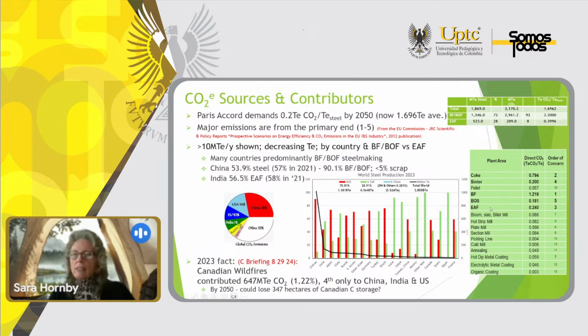But basically, the blast furnace is the largest on its own, 1.2 tons of CO2 per ton. The second is the coke at 0.79, and the third is the EAF that drops down to 0.24. Now, the Paris Accord demands that we drop to 0.2 tons of CO2 per ton of steel by 2050. And currently, the average across the world is about 1.7.